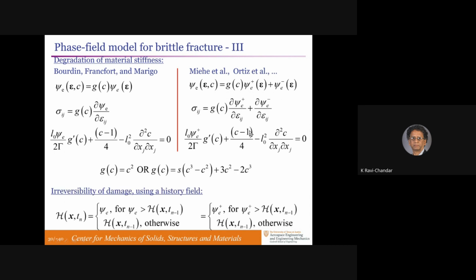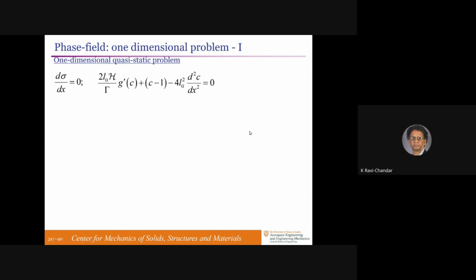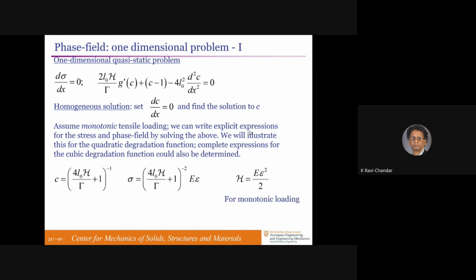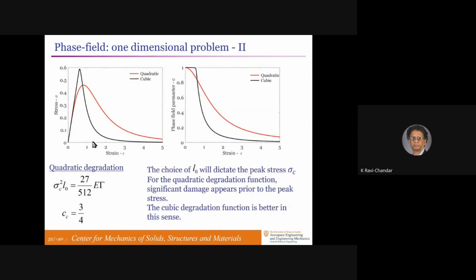And you can do the one-dimensional problem fairly easily. I'm skipping details again. Basically what happens is, depending on what your damage function is, the local behavior of the stress strain with the phase field would be linear up to some point, start damaging at some point, and then peak stress at some level, and then damage continues further, and the material is separated at this point. So you've converted the problem of fracture mechanics into one of elasticity or elastic calculation with this model. But crucial to it is that there's an intrinsic length scale that's been brought into it, and this length scale must be extremely small in order to capture the fracture process faithfully.